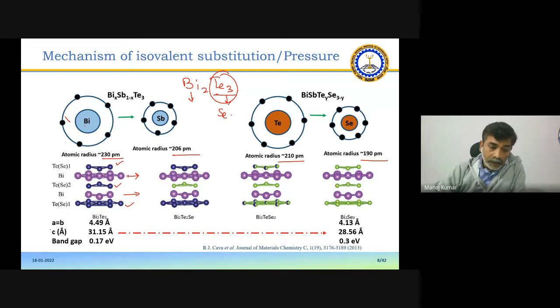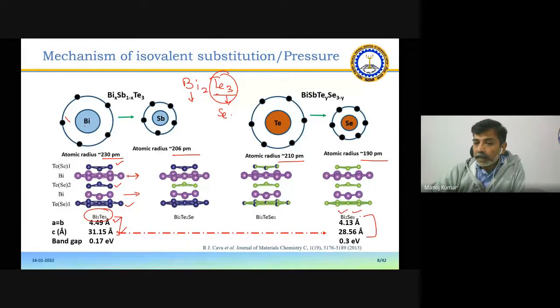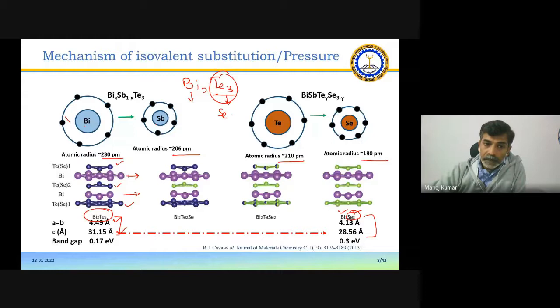And indeed, if we compare the lattice parameters, in case of both layer bismuth and all three layers tellurium, our lattice parameters are in this range, and the lattice is slightly bigger as compared to when we replace this with selenium completely, okay? So the similar effect takes place when we dope this, when we replace bismuth with antimony, okay? And this has impact on the band gap. Eventually, it increases the band gap in this material.